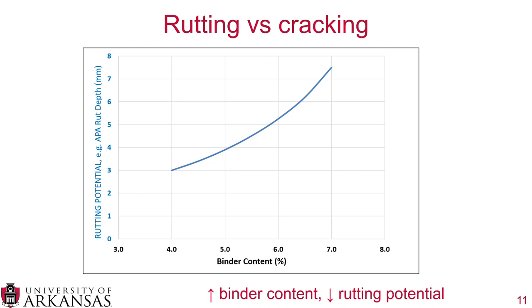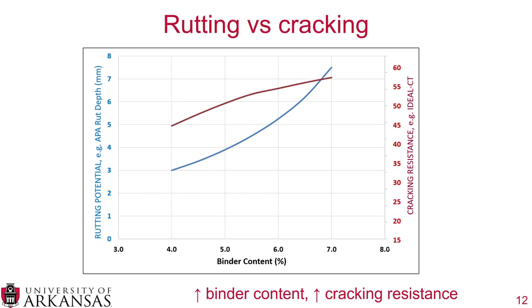Now you can think about rutting versus cracking also in a graphical format. So here you can see we have the binder content on the x-axis. It goes from 3 to 8%. On the y-axis on the left-hand side, we have what I call rutting potential. For example, this is just using the APA, Asphalt Pavement Analyzer, rut depth, which is in millimeters. And you can see here, as you increase the binder content, you decrease the rutting potential. Then on the right-hand side, the cracking resistance, which is represented here by the CT index, as you increase the binder content, you increase the cracking resistance.